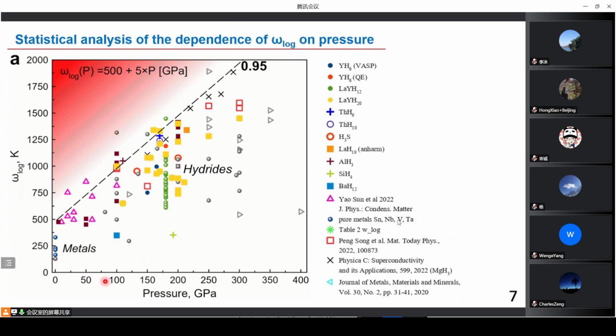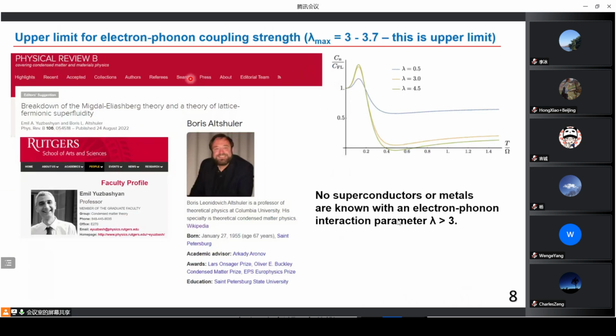So you can clearly see that 95% of the data is under a straight line, which can be described with this linear equation, linear function. And it means that in 95% of cases, when we increase pressure, we can get some benefit in the logarithmic frequency. In order to increase the logarithmic frequency, we need to increase pressure, and vice versa. Okay, it's a very useful result, and I will use it in the next slides. The next step is the upper limit for electron-phonon coupling strength.